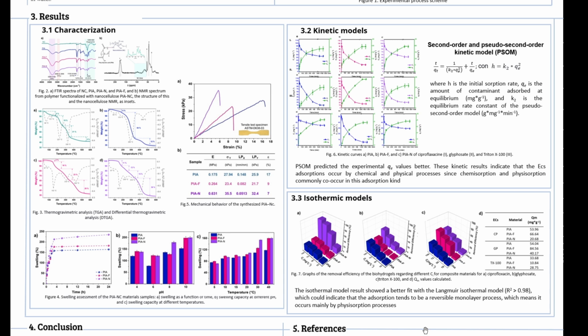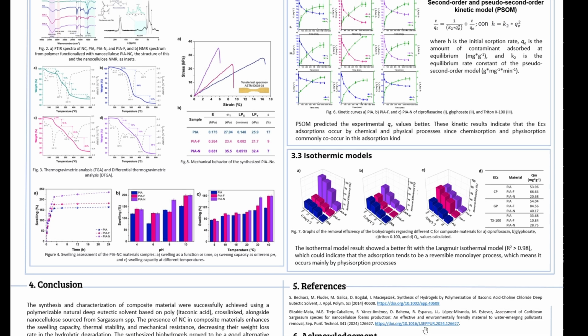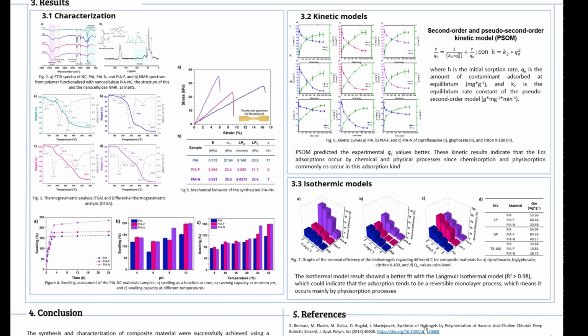The mathematical models used to study the removal kinetics were the pseudo-first order and the pseudo-second order, constructed from the obtained experimental removal data, resulting in the pseudo-second order model predicting the experimental load at equilibrium values better. This kinetic result indicates that the emerging contaminant adsorption occurs by chemical and physical processes, since they commonly occur simultaneously. Besides, the Langmuir and Freundlich adsorption isotherm models were applied to elucidate the adsorption mechanisms. These biohydrogels' maximum adsorption capacity and the removal efficiency percentage were determined for each emerging contaminant.